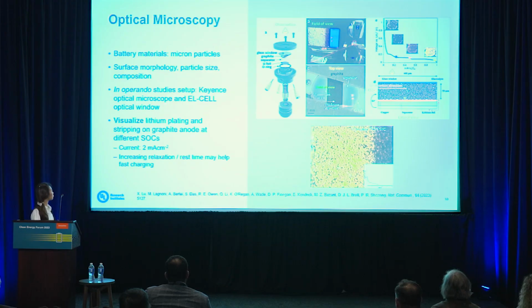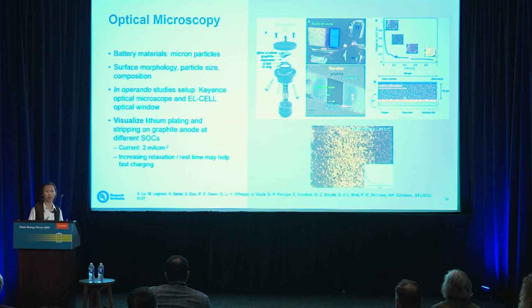The authors found that if you have a relaxation or a rest step, that can help with fast charging, to allow the battery to relax a little before discharging. And similarly on discharge, you can see that the front moves in the opposite direction. So it's a very good visualization tool.